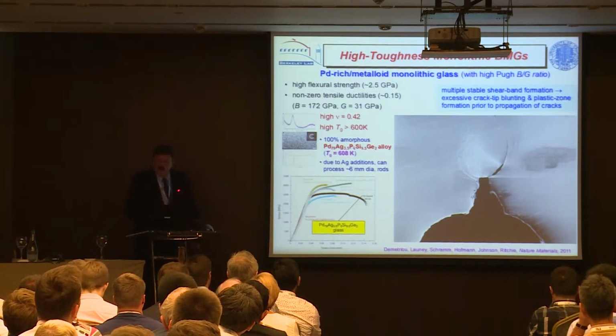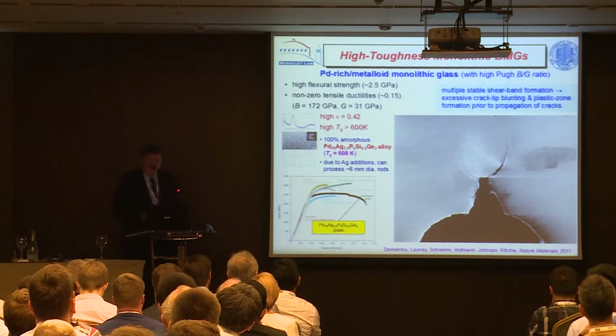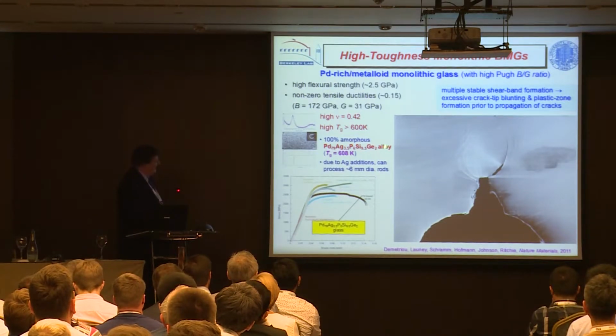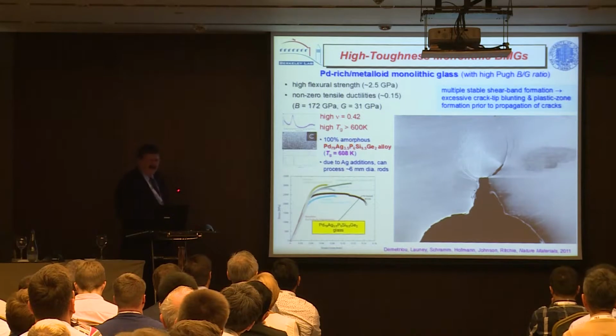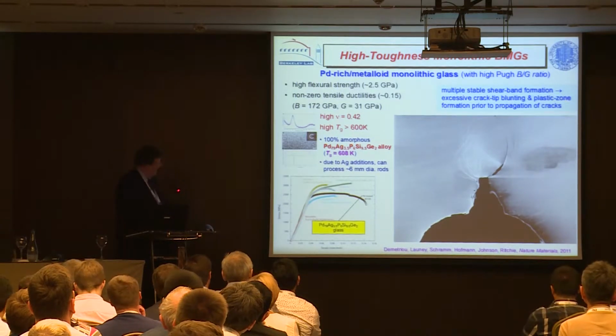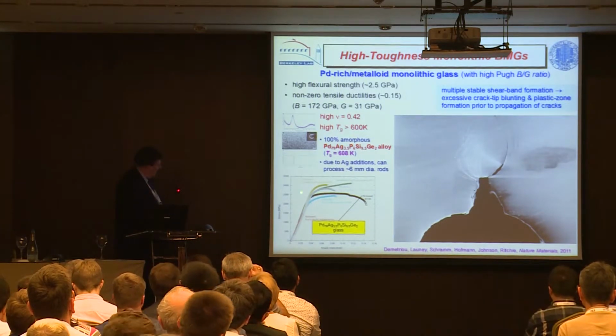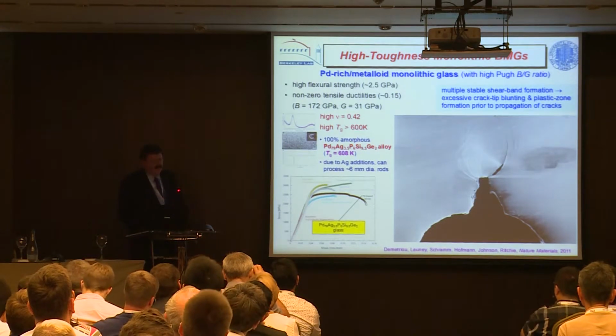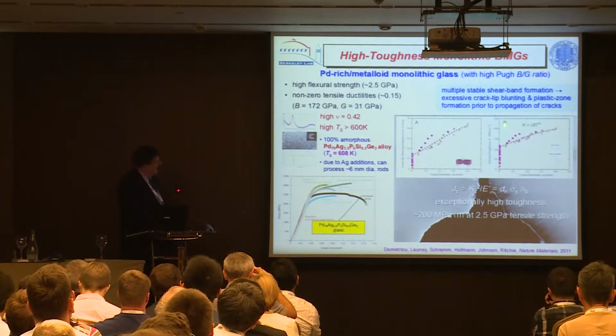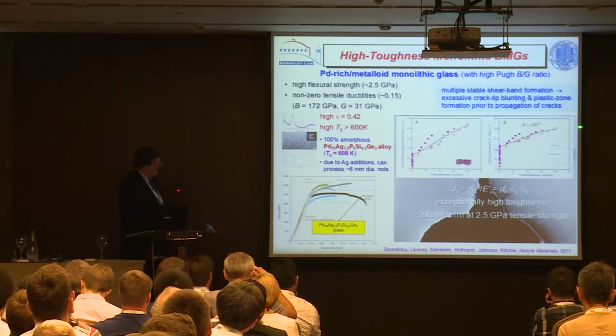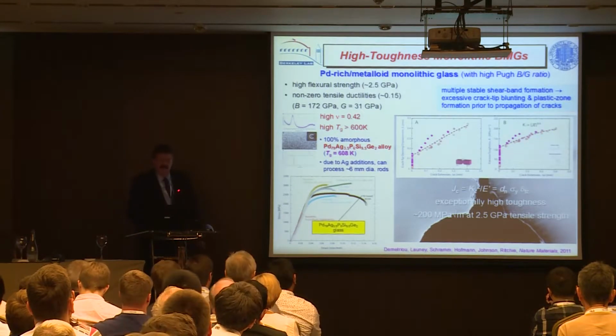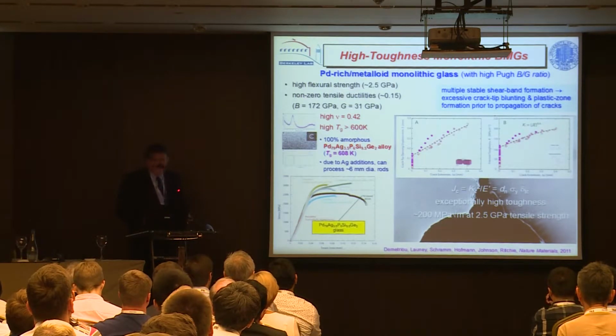We made one with a palladium-containing glass. It's obviously not very practical because palladium is about $1,000 an ounce. And we made this material, and it was remarkable. You saw by the image, you get very tremendous ductility. We got a bending strength here of 2.5 gigapascals, and we did toughness tests on this, and we got R curves with toughnesses up to 200 megapascal root meters.